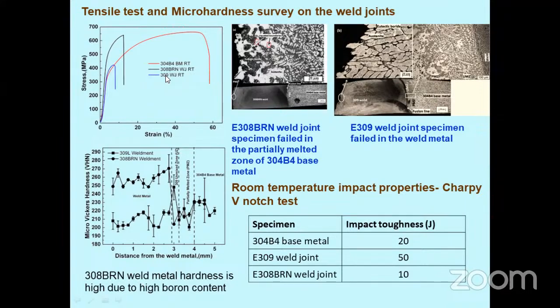prepared using the boron free electrode, that is 309. We can see that both are deteriorated. It is not as comparable to the base metal, but it has adequate strength. The borated electrode has a very good strength, but the boron free electrode has an adequate strength.